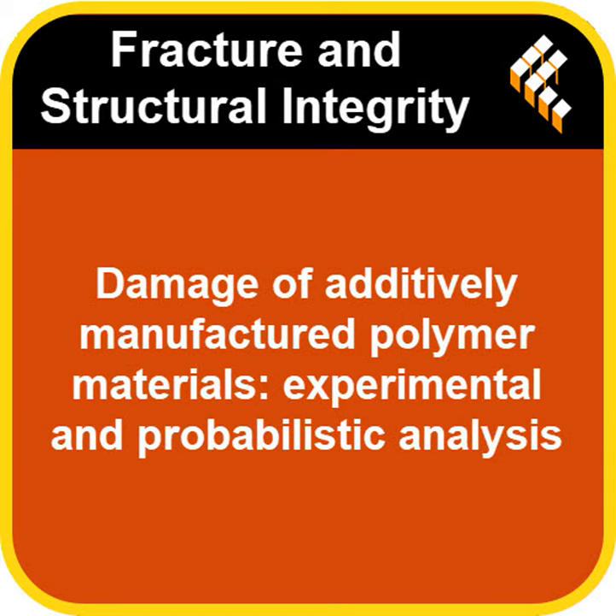No, actually fix it, in a way, by excising the pre-cracked region. Excising. You mean cutting it out? Essentially, yeah. Carefully cutting out the damaged area, which would reduce the specimen's overall width slightly in that region, but it removes the defect entirely. Like performing surgery on your 3D printed part. That's a great way to put it. Exactly. The logic is simple and compelling.